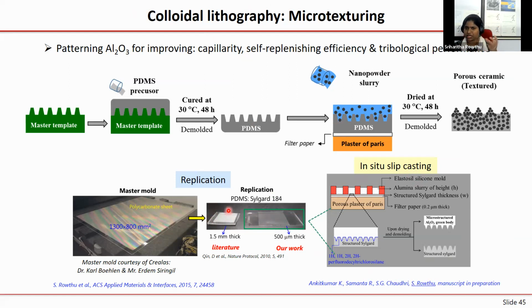But for our tribological test, we need bulk specimens. So if you want to make bulk specimens, in the slip casting, in the same assembly that we had, between the filter paper and this silicone mold, I'm going to place this thin Sylgard here. So that I am able to pour quite a lot of slurry into these molds, and finally achieve very big green compacts, wherein this interface, the slurry and the PDMS interface, is where my texturing is going to happen.